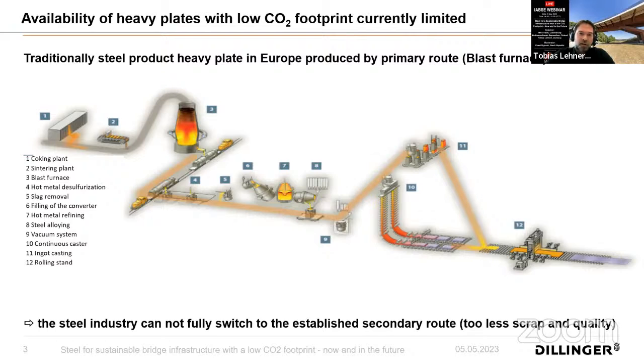And as it was explained in the last presentation, this primary route, the blast furnace, using iron ore and having the iron ore reduced by coal or coke in the blast furnace, emits a lot of CO2 emissions per ton of steel. And it is currently not possible, due to quality reasons but also just due to the availability of scrap, that the whole steel industry switches to a secondary route. So even in the future, we will always need a primary route which brings new primary steel into this circle of recycling. So that means that for the product of heavy plate, the availability is currently quite limited of steels with low CO2 footprint.